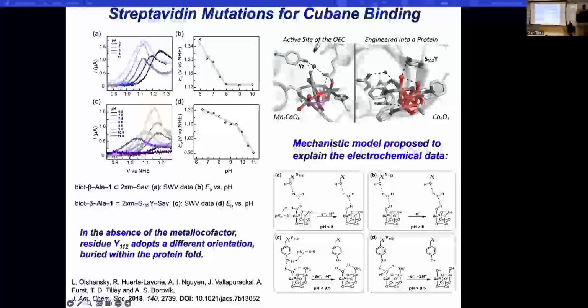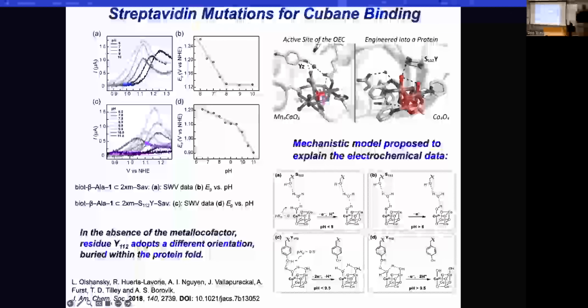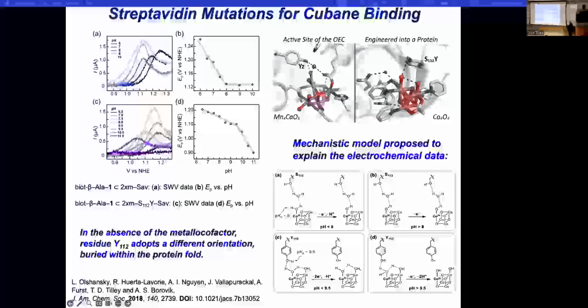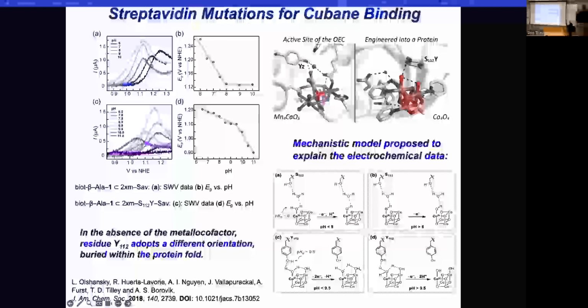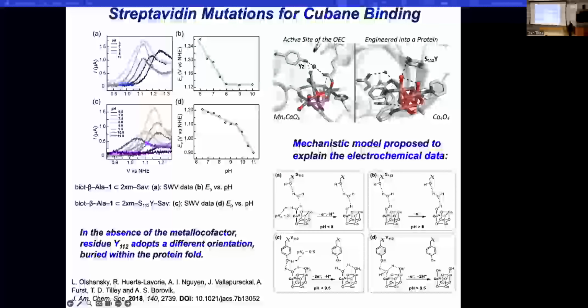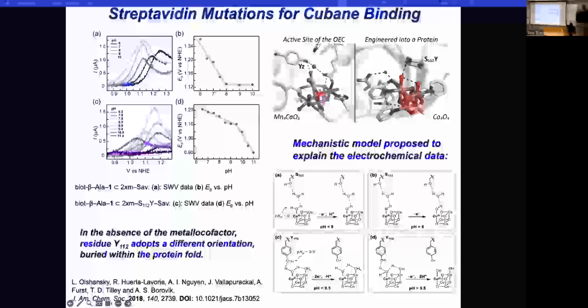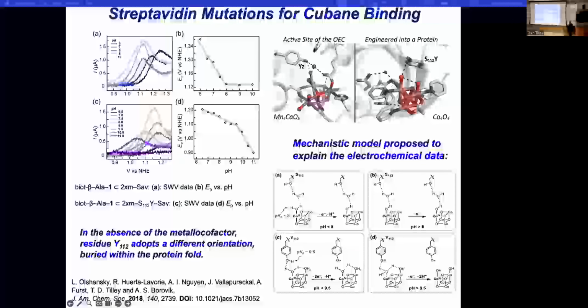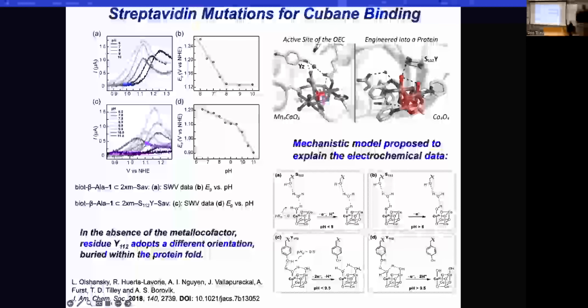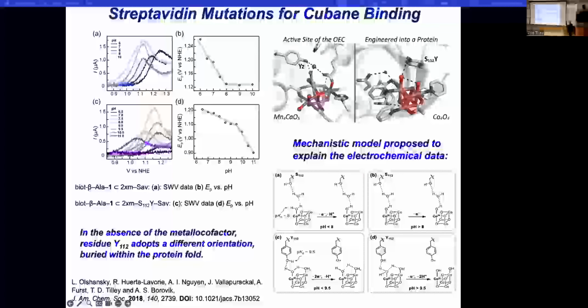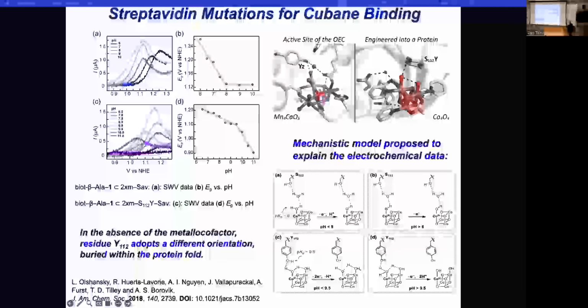And so this is a good mechanistic model for the natural system, because in the OEC, you also have a tyrosine hydrogen bonded to the cube. And this tyrosine is acting as a proton electron relay for electrons and protons going in and out of that reaction center. And what we're able to show with electrochemistry is that the same thing occurs here in the cobalt system. It's just that the oxidations are in the wrong direction, right? But nonetheless, we could come up with a pretty simple model to explain the pH dependence of the oxidations of this system with and without the tyrosine there. As you can see, big difference.